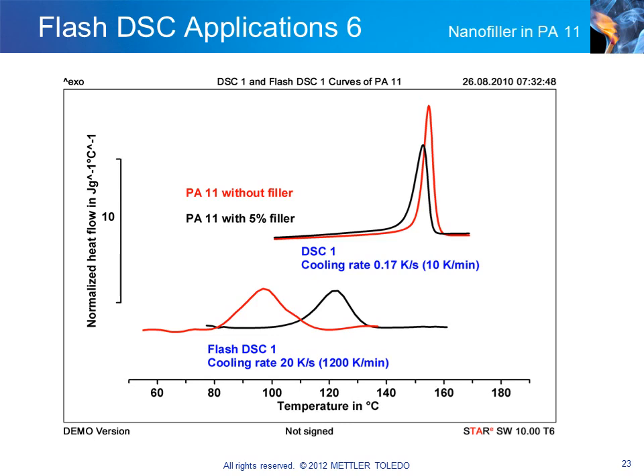In this application, differences in nucleation were investigated by varying the cooling rate. Samples of polyamide 11 with and without filler were cooled in a conventional DSC at 10 degrees per minute and in the Flash DSC-1 at 1200 degrees per minute. The red curves are of a pure polyamide without filler. The black curves were measurements of a polyamide that contained 5% nanofiller.